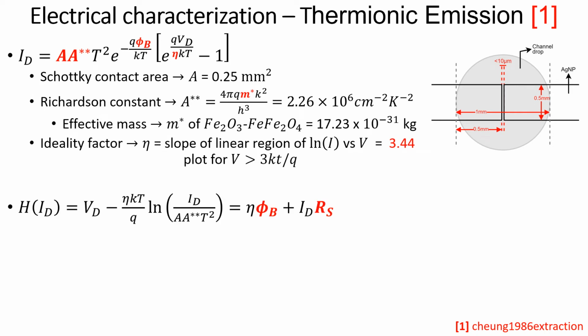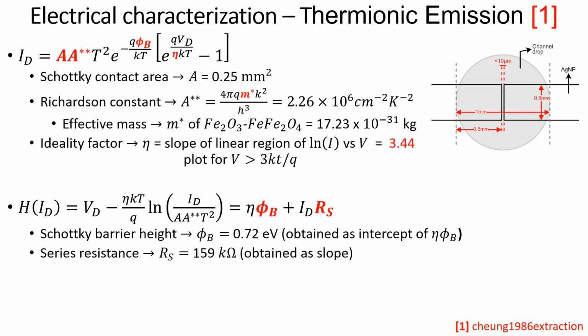For the calculation of phi B, that is the barrier height, we require to modify the equation to the following format. What we basically do is bring the A star T square to the left hand side of the equation from the base equation, and then we take log on both sides, and after doing several algebraic exchanges, we get the following equation. The Schottky barrier height is computed as 0.72 electron volt, and the series resistance is computed as 159 kilo ohm. We obtain this from the intercept and the slope of the H(I) versus I graph.